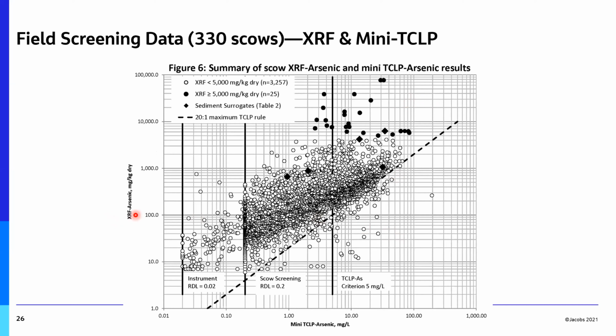So here is our XRF arsenic totals versus our Mini-TCLP. What we're actually showing you in this plot is our sediment surrogates that were used for our treatability study. And at the end of the day, we actually picked pretty well. These are our 2 soft dredge material, actually 3 soft dredge material samples, because we had another one mid-project. And then these are our 2 semi-consolidated materials. You can see we had a number of hits up here, but these are initial hits before reblending, right? So when you reblend those, you knock those back down and we were able to treat them.